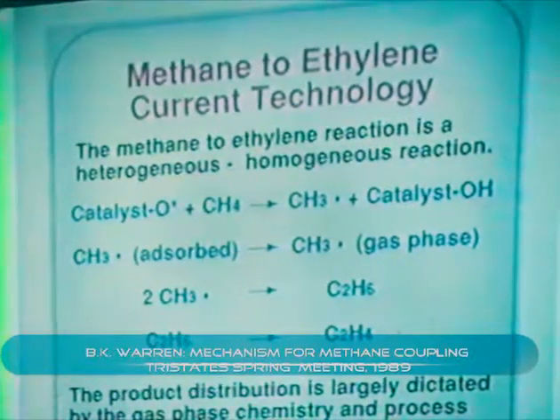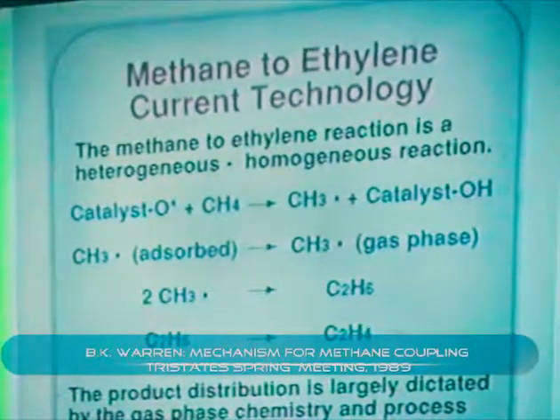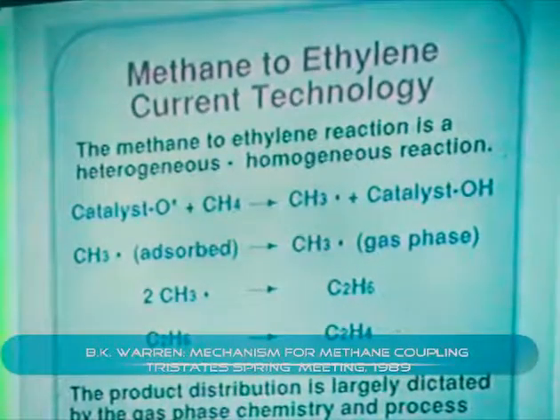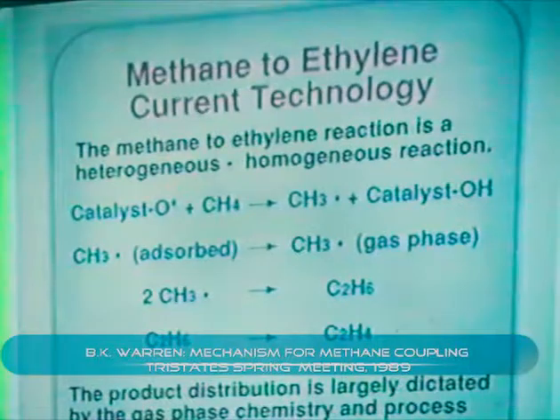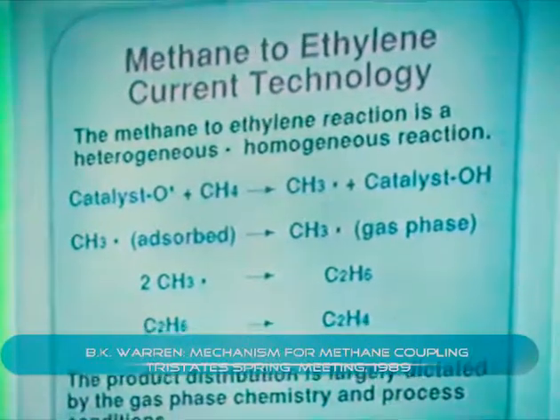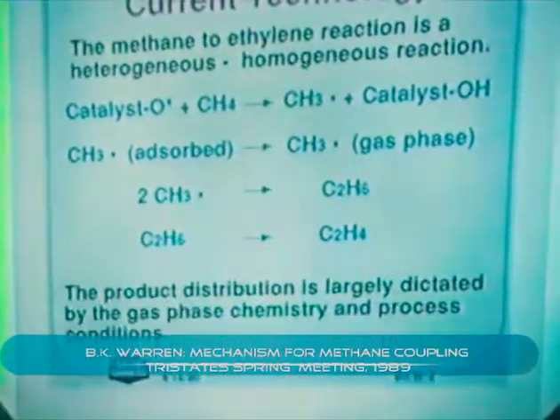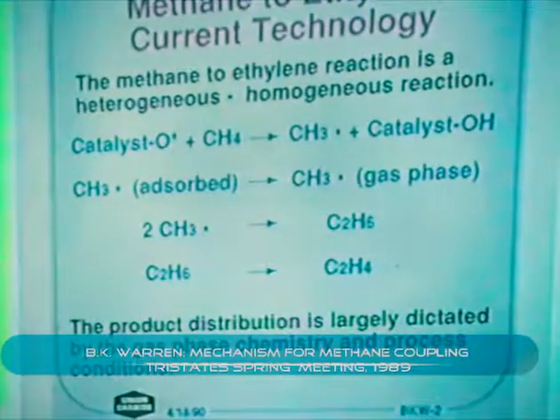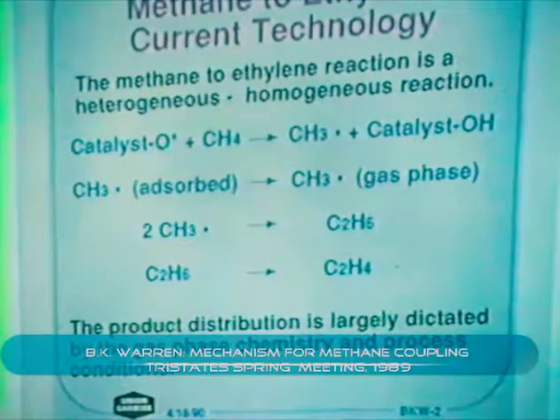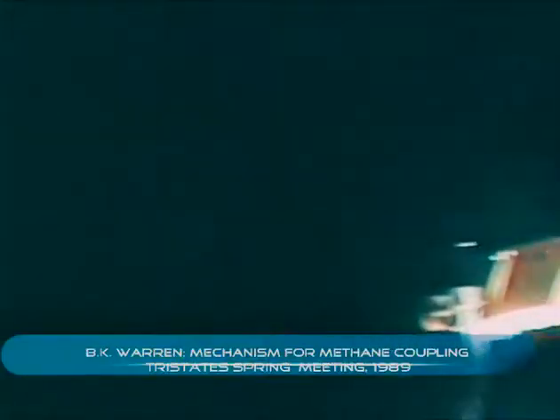In fact, this reaction has been reported with a number of catalyst systems, and the mechanism presented in this slide is Jack Lunsford's mechanism for a variety of solid materials for the conversion of methane to ethylene, which is a reaction conducted at very high temperatures, usually between 750 and 900 degrees centigrade, and generally close to atmospheric pressure. It involves the extraction of hydrogen from methane by an activated oxygen on the catalyst to produce a methyl radical, which is then released from the catalyst surface into the gas phase, where two methyl radicals couple to form ethane. Ethane is subsequently converted to ethylene by well-known homogeneous reactions in the gas phase.